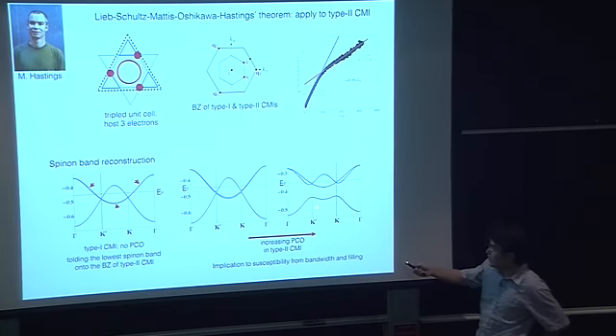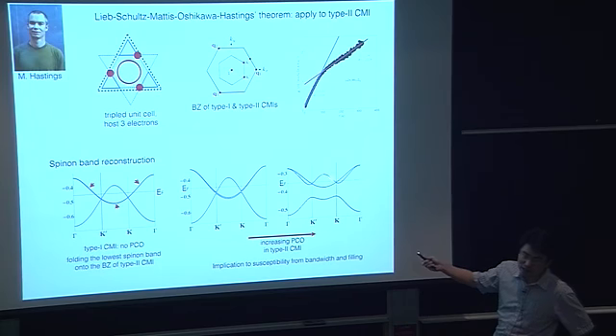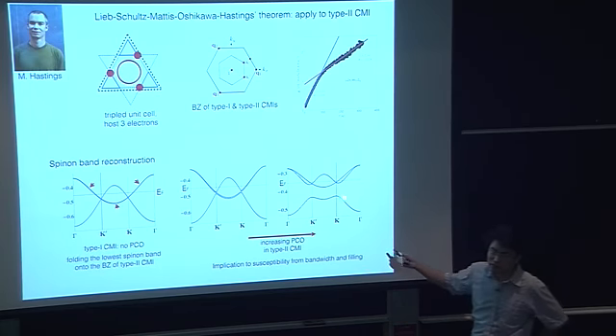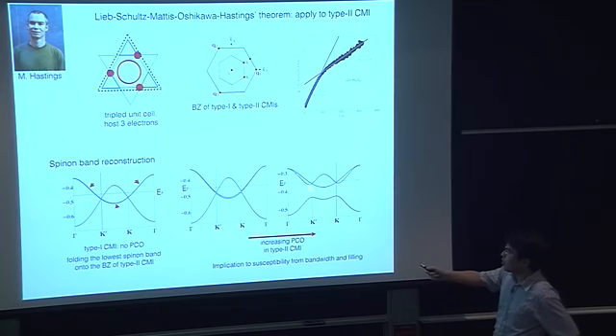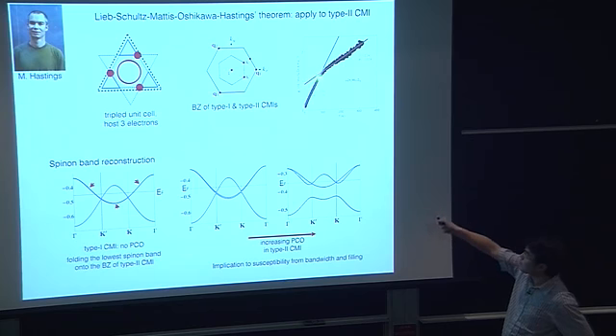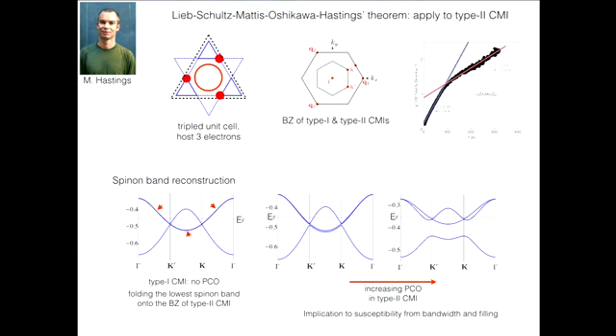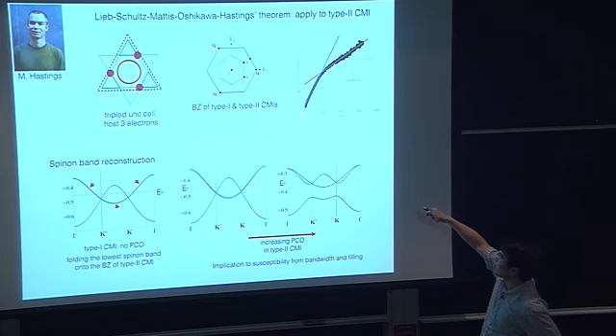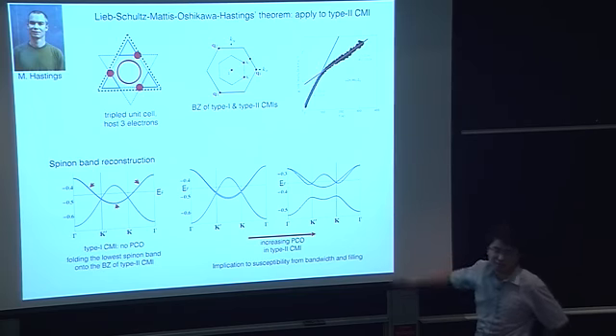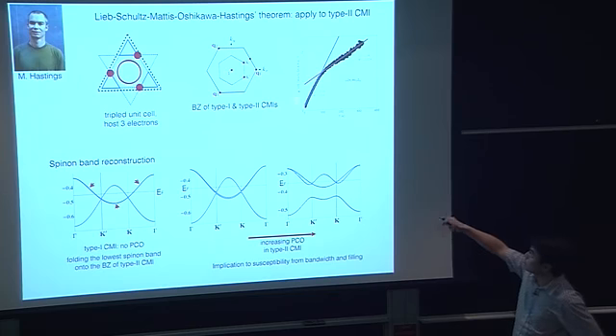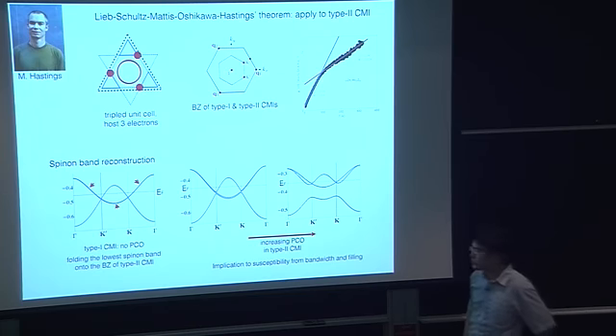There are exactly 1/3 of the total number of electrons in the partially filled band. At finite temperature, at low temperature, this 1/3 of the electrons will contribute 1/3 of the Curie constant. So that will explain why there is a 1/3 spin susceptibility anomaly at low temperature. The Curie constant measures the number of active local moments, so the moments are only 1/3 of the total number of electrons here.